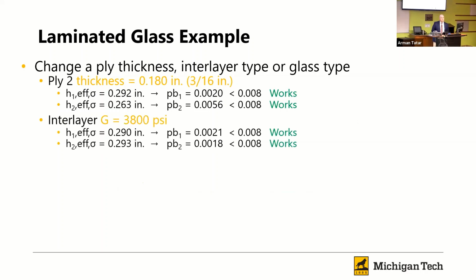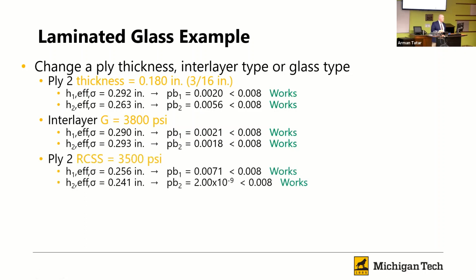Alternatively, we could have used a stiffer inner layer. So instead of using the PVB inner layer, I could have used something more consistent with an ionomer inner layer. And we see that that G value goes way up, and now it works. So I didn't have to change the glass thickness. I just changed the inner layer I chose to use. Also, I could have chosen to heat treat that ply. And we see that when we do that, that one goes way down, okay? So we have several different options there on how we can change the configuration and make the system work.